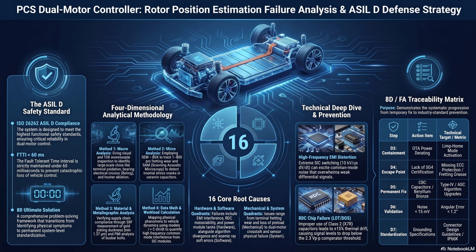It uses a complex matrix equation that relies heavily on a fixed parameter, the physical resistance of the copper stator windings. But the resistance of copper is not a fixed parameter at all. It has a positive temperature coefficient. Yeah, very much so. As the motor runs hard and the internal temperature climbs from, say, 20 degrees to 130 degrees Celsius, the physical electrical resistance of that stator winding increases by roughly 40 to 50%. And that introduces sensorless control divergence. Because the math is wrong now.